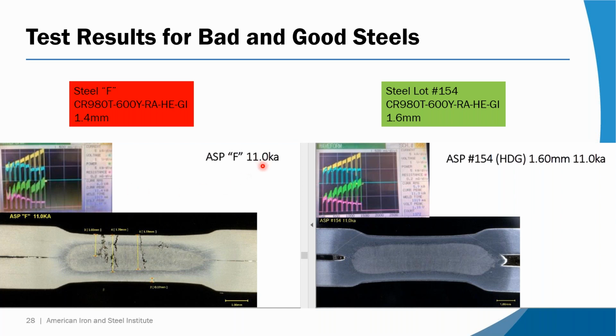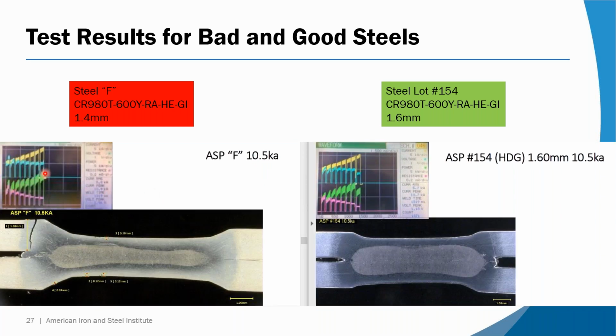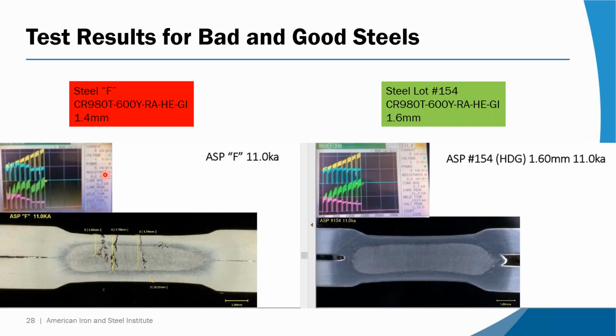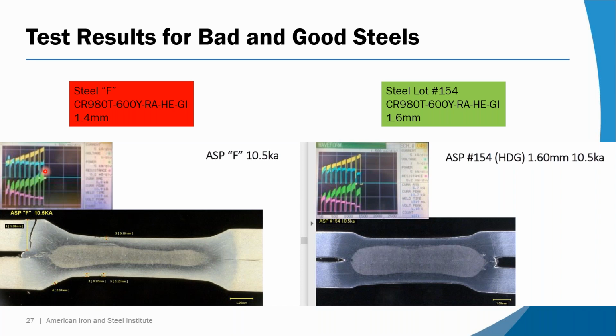If you look at this, this is Weld at 11 kiloamps. If we go back to 10.5, our peak power occurred on the last pulse. Here, our peak power is not so much the last pulse, it was also in the 5th pulse. But the Weld before, which was at lower current, actually finished at a higher power level.